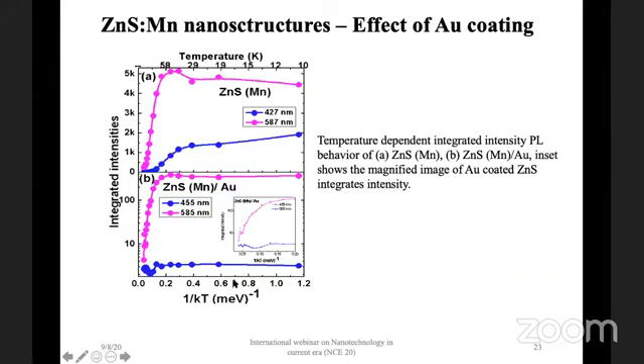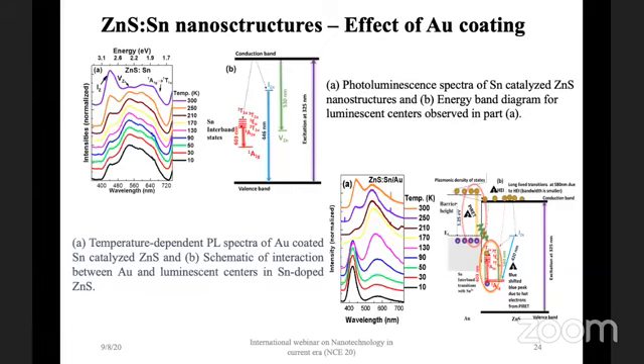We plotted the Arrhenius plots of these ones, and we see the intensity behavior is showing abnormal behavior. It's not normal. We see amplification of these modes as the temperature increases, which means the transfer of energy is seen. We fitted these with the Arrhenius plots, and we determined the various activation energies and Arrhenius plot energy from these nanostructures. And we are actually trying to quantify the role of plasmons in this transfer mechanism. Now we have another set of experiments, zinc sulfide doped with tin, and now we did a coating of gold on these ones.